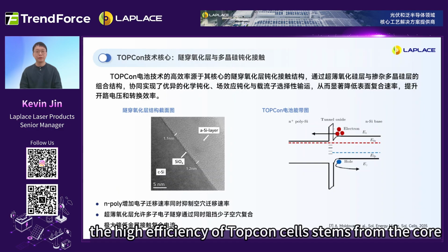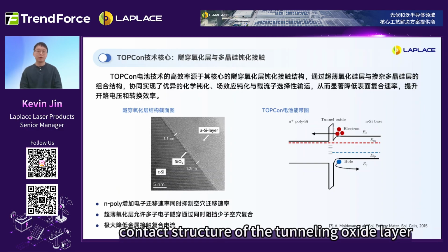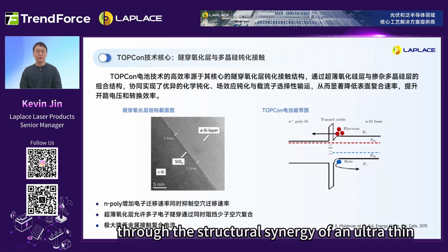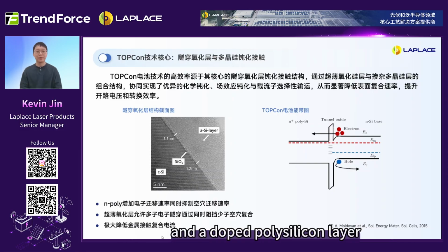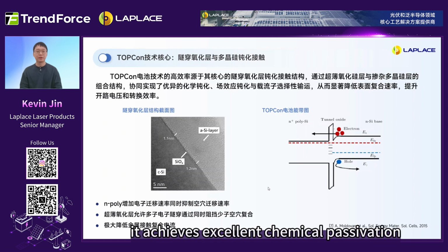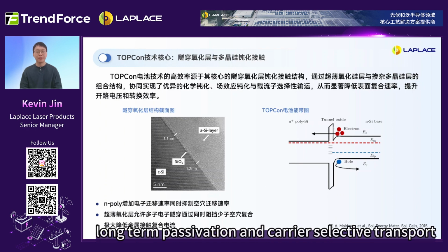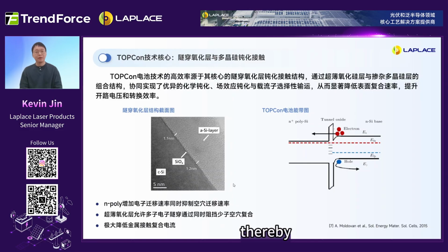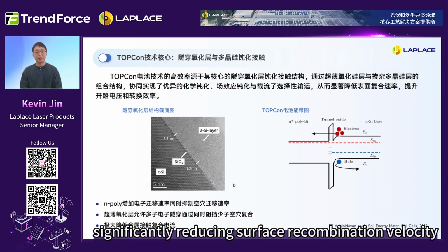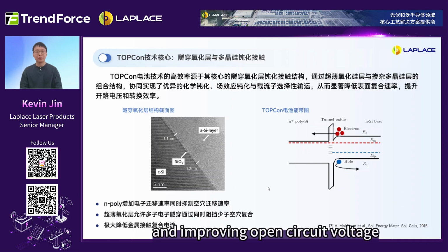The high efficiency of TOPCon cells stems from the core passivation contact structure of the tunneling oxide layer. Through the structural synergy of an ultra-thin silicon oxide layer and a doped polysilicon layer, it achieves excellent chemical passivation, field-effect passivation, and carrier selective transport, thereby significantly reducing surface recombination velocity and improving open circuit voltage and conversion efficiency.